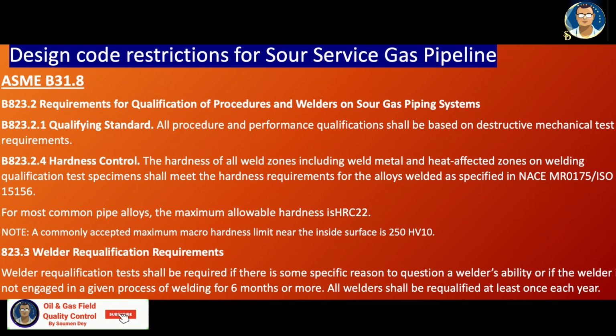In the field we need to take care of the heat input during welding. If you control the heat input, the hardness will be under control also. For most common pipe alloys, the maximum allowable hardness is HRC 22. A commonly accepted maximum macro hardness limit near the inside surface is 250 HV10.